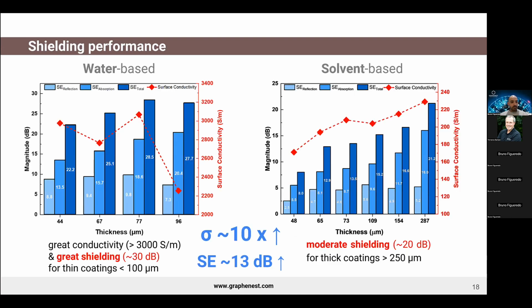On this slide, I'm plotting the shielding effectiveness of the two versions, water-based and solvent-based, as a function of the thickness. And in red, we can also see the surface conductivity of both products. What is immediately possible to observe is that the surface conductivity of the water-based is 1 order of magnitude higher. So we have 3,000 Siemens per meter for the water-based, while the solvent-based is in the hundreds. And because of that, the shielding performance of the water-based is also better. We are talking about an average of 13 decibels of difference, regardless of the thickness.